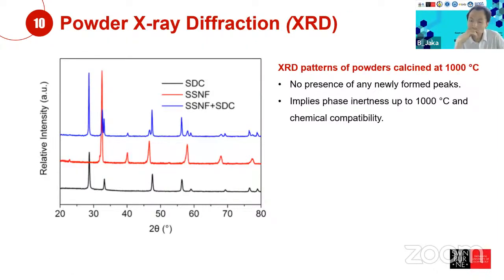Okay, now we also check again using the powder X-ray diffraction pattern. Mainly, we focus on the SSNF with the SDC mixture because we would like to know if there is any additional phase formed after we combine this SSNF with the SDC mixture and heat it up to 1000 degrees Celsius. If we have extra peaks that cannot be indexed with respect to the individual components, SSNF and SDC, that means we have a new phase formed, which can come from reactions between the components. So in here, we don't see anything, because all the peaks from the mixture of SSNF and SDC heated up to 1000 degrees Celsius can be indexed with respect to the peaks of SSNF and SDC. So our mixture is quite stable when we heat it up to 1000 degrees Celsius.